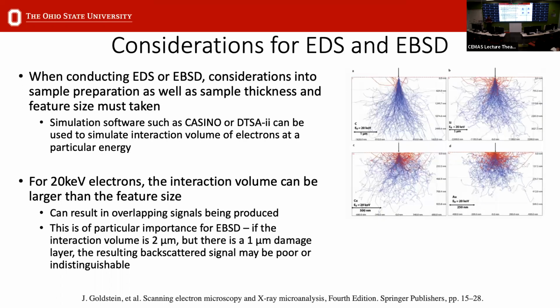So when talking about sample prep, we talk about what you need to do to make your sample optimal for the technique you're going to use. So when you're doing EDS and EBSD, there are many considerations to take into account. One of the biggest considerations is the interaction volume of your beam. Typically, if you're going to use EDS or EBSD, you want to use a higher voltage in the SEM, typically 20 kV or above.